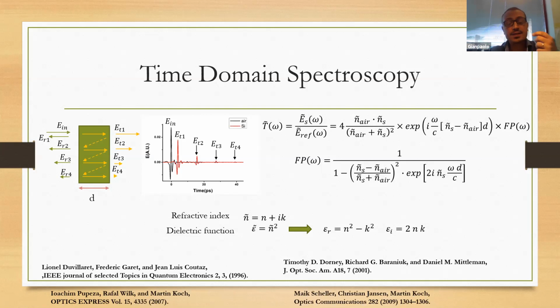To make spectroscopy of this sample means to pass to the frequency domain. So we apply the Fourier transform of the signal passing through the sample divided by the Fourier transform, fast Fourier transform in this case, of the reference signal. This is a classical model where we can, according to the Fresnel coefficients and the phase accumulated by the signal after the thickness D, write these simple expressions. And of course, the periodicity of the reflected signal provides Fabry-Perot terms that in transmission are featured by clear harmonics related to the refractive index and the thickness of the sample.